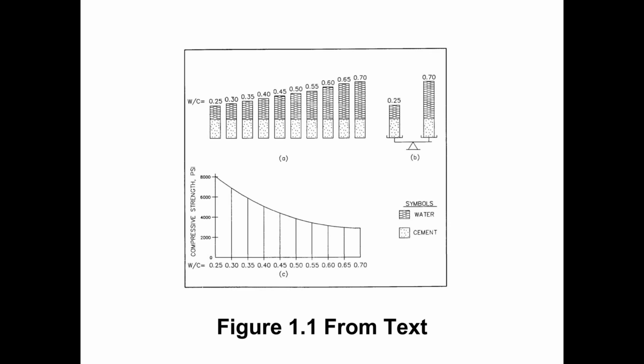But since we started with more material because we had more water, the volume of these different samples will be a little bit different. The samples with higher water cement ratios will be a little bit larger than the samples with the lower water cement ratios. So even though they all weigh the same, they do not all occupy the same volume. So if you have a sample of material that was at a water cement ratio of 0.25 and a sample of material that was at a water cement ratio of 0.70, those two samples, they weigh the same. That's what figure B is showing you there. But the sample with the higher water cement ratio is going to be larger.